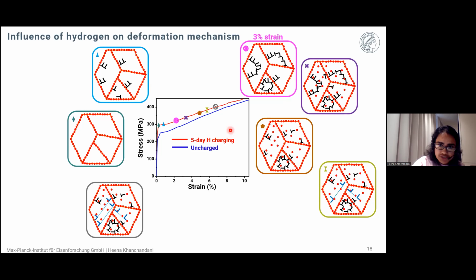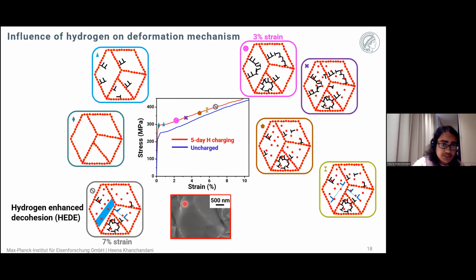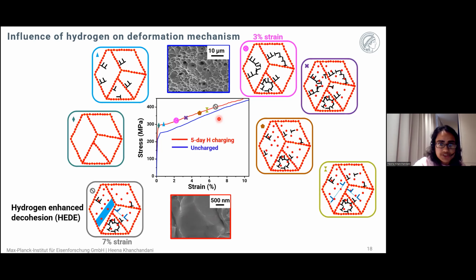And these stacking faults, which are observed at 7% of strain, stack together to form these epsilon martensite plates. These plates are impinged in between grain boundaries, which leads to the embrittlement at grain boundaries by the hydrogen-enhanced decohesion mechanism, which is why the fracture surface of the hydrogen-charged sample has intergranular features at 10% of strain, which is different from the fracture surface of the uncharged sample, which has these ductile features. So this shows how hydrogen modifies the deformation mechanism and leads to the early embrittlement of the material at grain boundaries. So by now it was clear that grain boundaries play a significant role.